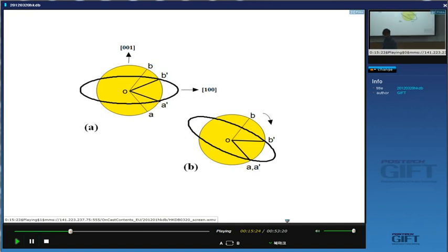If I give you the lattice parameters of austenite and the lattice parameters of the ferrite, then you can calculate the Bain strain, and you can calculate the rotation required to generate an invariant line, and that gives you the exact orientation relationship between the austenite and ferrite, and it's only a function of the lattice parameters of the two crystals.